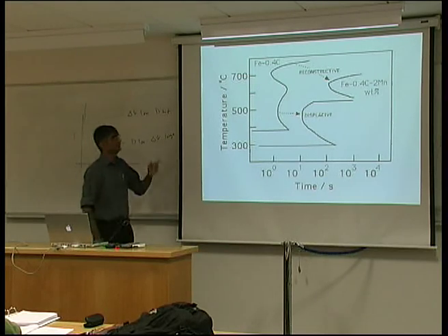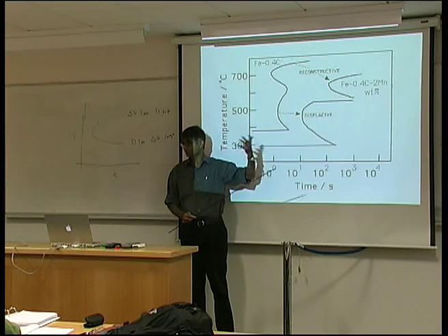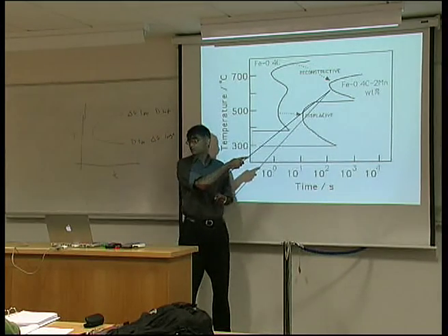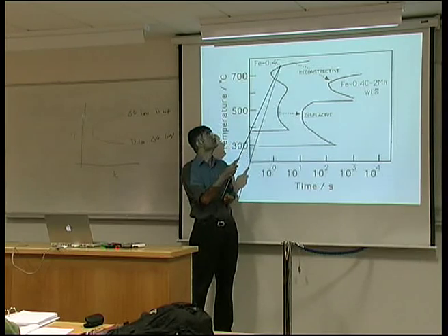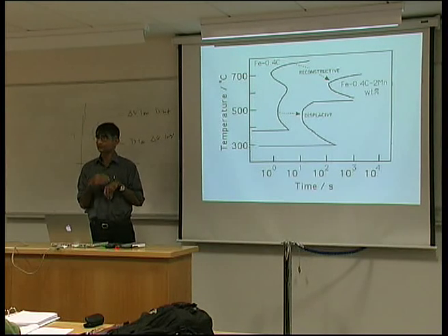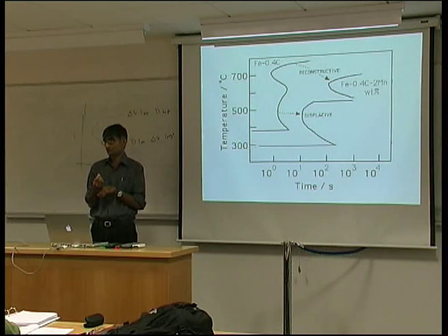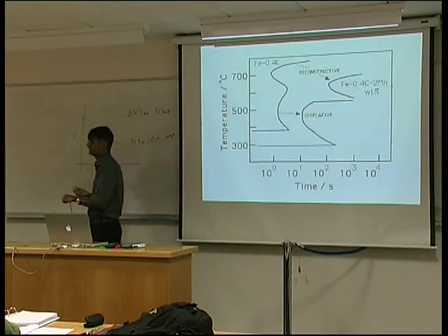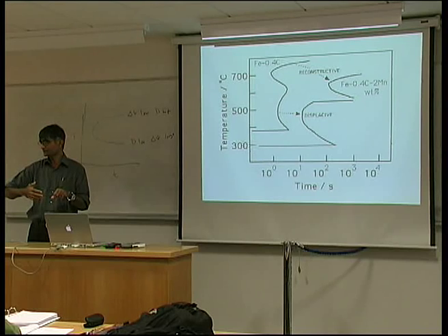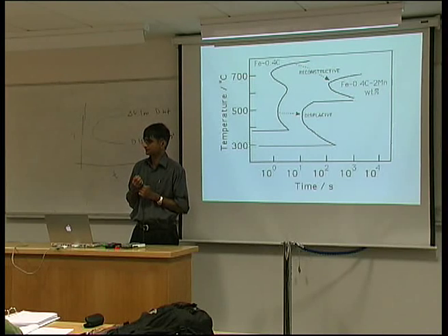Exactly right. So, of course, manganese will affect the thermodynamics of both kinds of reactions. The free energy change will be altered, whether it's a displacive or a reconstructive transformation. But in this case, the manganese has to diffuse during transformation, and that really does have a large effect on retarding the reaction. So for reconstructive transformations, there are two effects. One is the thermodynamic effect: the free energy change is influenced by the addition of manganese. And the second factor is that these elements will partition between the parent and the product phases, and therefore will slow down the transformation by the need for diffusion.